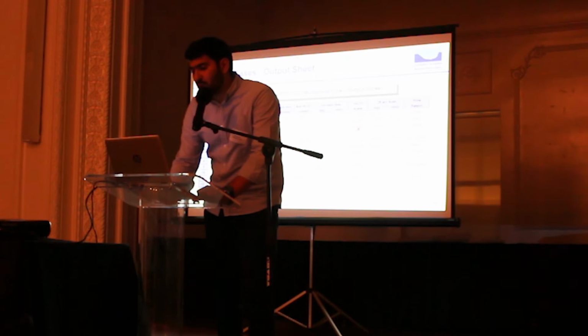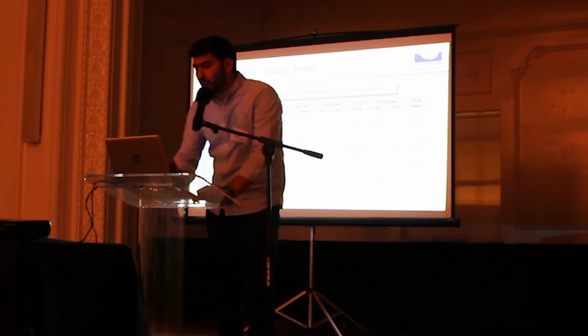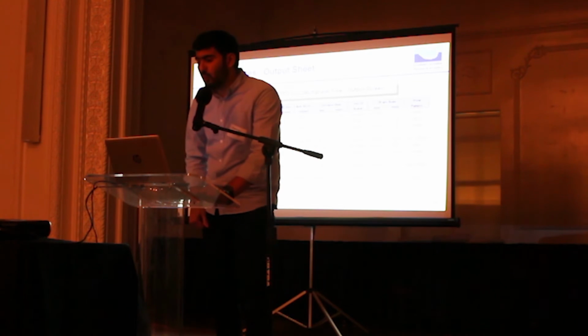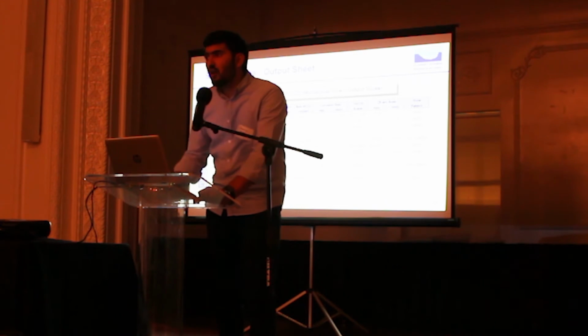Okay, but how good is the scale? We can tell by the corrosion rate here. If you look at the two cases here, we have two scales. If you look at the corrosion rate, the one with high pH has lower corrosion than the one with low pH. So what I can notice here is that higher pH is giving me a scale that is more protective against CO2 corrosion. And this just depends on the properties of the scale. If we have the scale formed at low temperature, then it's going to be fluffy and soft.